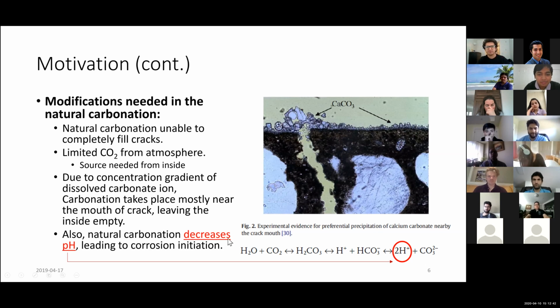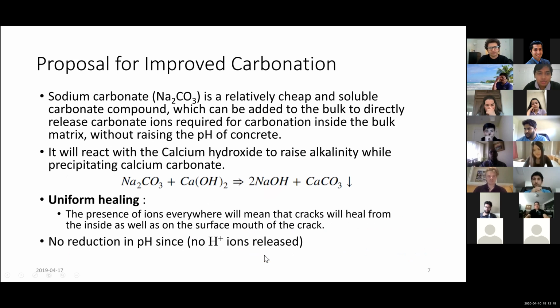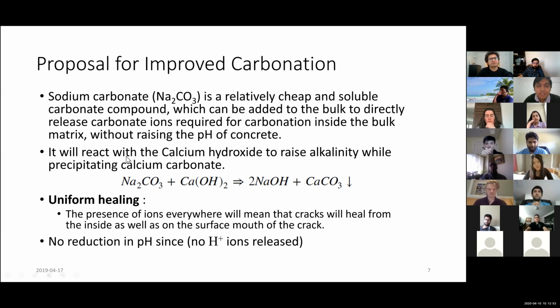As we have seen before, it decreases the pH in itself. So my proposal for improved carbonation using sodium carbonate is to provide carbonate ions directly without getting dissolved carbon dioxide from outside. This should react with calcium hydroxide to increase the alkalinity as well as produce calcium carbonate. So this time we are not reducing the pH, we are actually increasing it. This should support the precipitation as well as prevent corrosion from happening. And since sodium carbonate is now inside the matrix, it should be able to heal cracks from inside as well, not just from the surface.